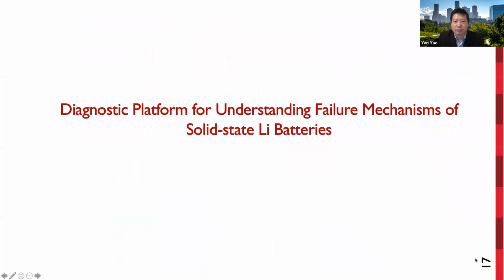So this work shows our effort in using earth-abundant materials that can potentially lower the cost and reduce the reliance on any metals. There are also still many challenges to overcome, such as the low density of organics, or reducing the electrolyte thickness to less than 50 micrometers to improve the volumetric energy density and rate performance. So that's the first example.